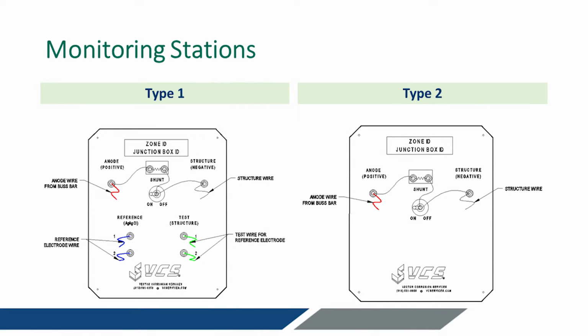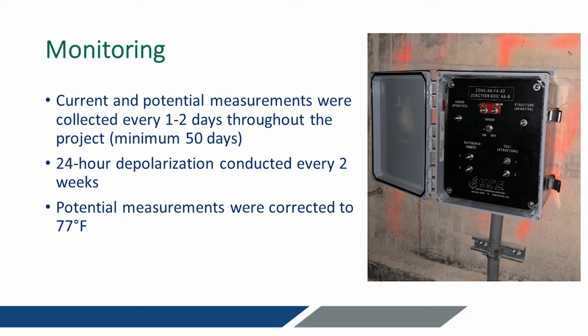And the monitoring stations, like I said, about 62, so we had little junction boxes throughout the structure so that somebody with a multimeter could go in and get the collected data from those zones. They had different types out there, but this is what they look like in the field. So an engraved panel with some sensors, reference electrodes that you can measure the potential of the steel, and then allow for measuring the current between the anode and the structure. So during installation, my team was out there doing QA/QC, verifying that the anodes were installed properly, and as the monitored zones came online, collecting daily measurements for performance to make sure the anodes are performing properly, and checking to make sure that everything is working correctly.